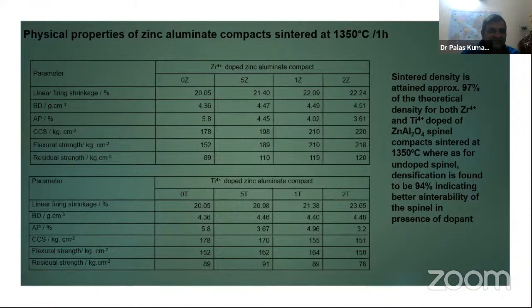Now, there are other properties like CCS, cold crush strength, flexural strength, and residual strength. For zirconia, with increasing dopant concentration, it gradually increases. Just one point I have to mention, this CCS value or flexural strength residual value is not the absolute one. This is just for comparative study. So you may not find the exact value of the CCS as per ASTM standard or standard protocol. If it is measured, definitely this value will be much higher. But our actual intention is to compare the properties in presence of dopant, and we are using this co-precipitated gel. Our volume is very low. Our major concentration in this investigation is other properties, especially electrical and optical, and microstructure and phase assemblage. But yes, just for comparative purpose we put it here.